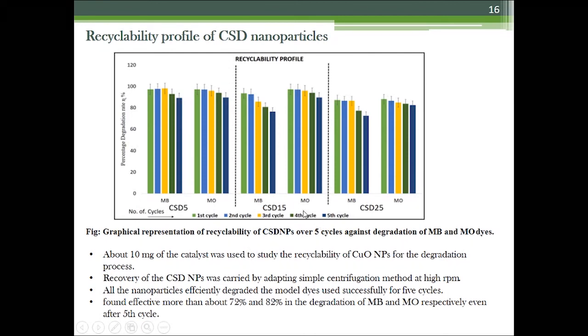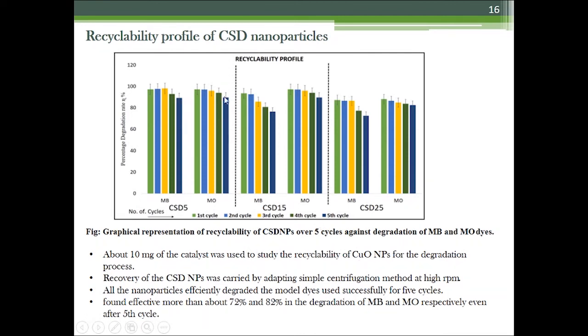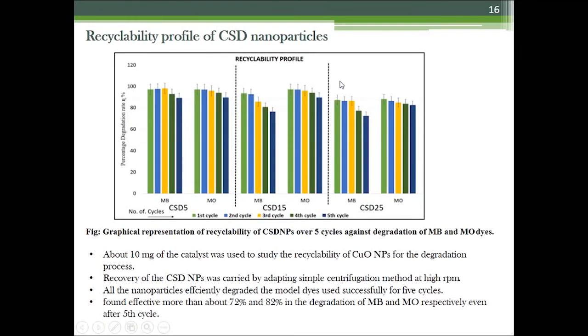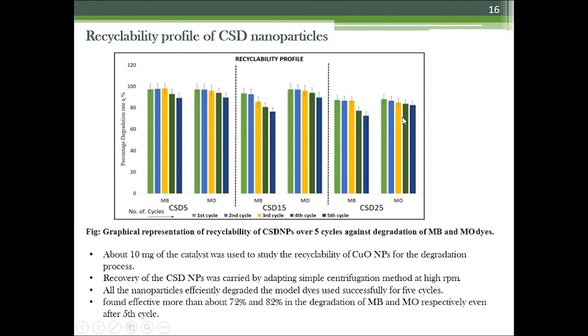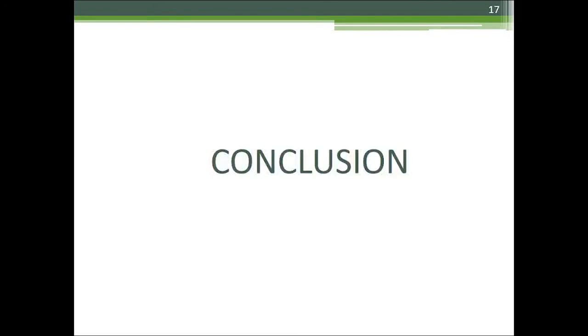There is a slight decrease in the photocatalytic efficiency. Here you can see the percentage degradation of dye is slightly decreasing. So there is a slight decrease in the photocatalytic efficiency rate after each successive cycle. This may be due to the loss of photocatalyst by weight after the recovery process.